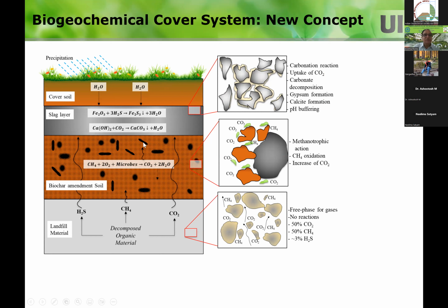So that methane oxidation produces CO2. This CO2 comes up, and the CO2 from the waste comes up, and the H2S from the waste comes up to the slag layer. So we are proposing having a slag layer. In the slag layer, you are sequestering the CO2 as calcium carbonate, and the H2S as iron sulfide. And then on top of this, you have a vegetative cover soil to put the plants. This does not have to be any engineered soil. You can just put a soil that can support the vegetation. It could be permeable, and we want some water to infiltrate, because we want the slag layer to be a little bit wet.